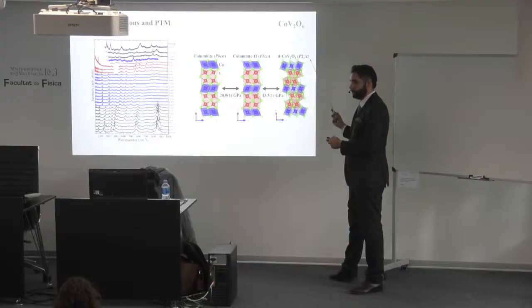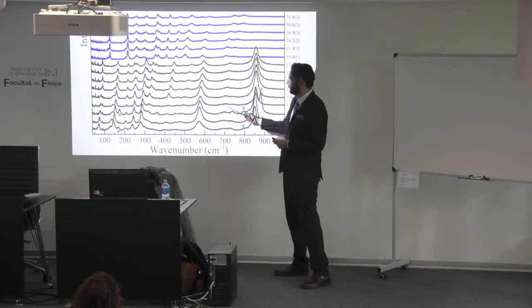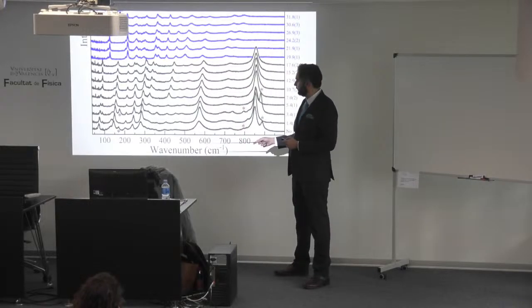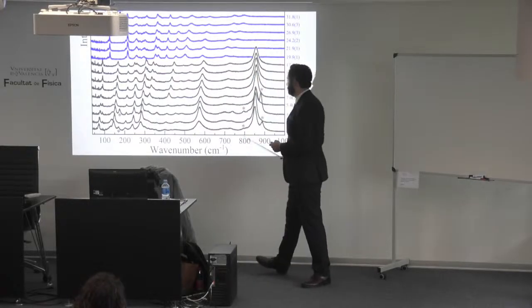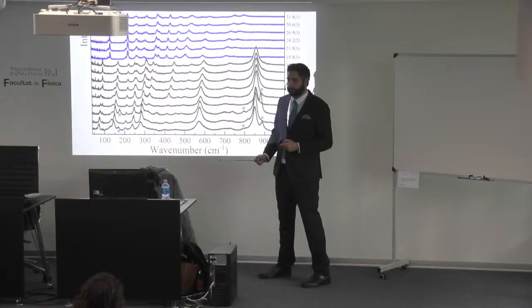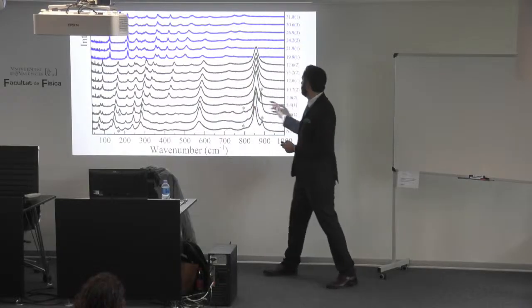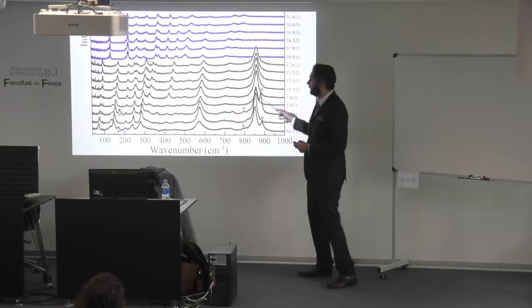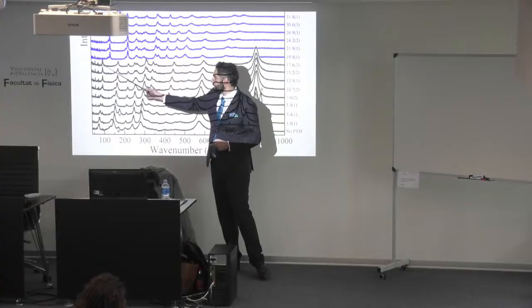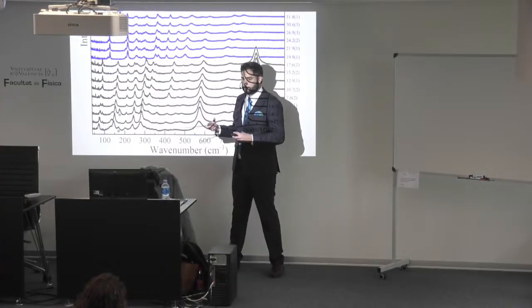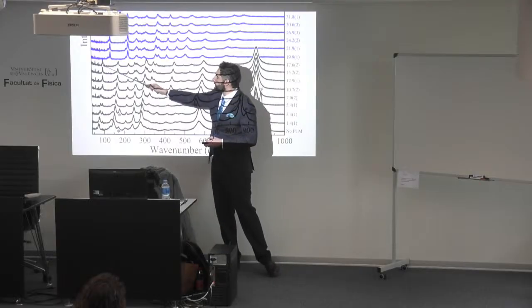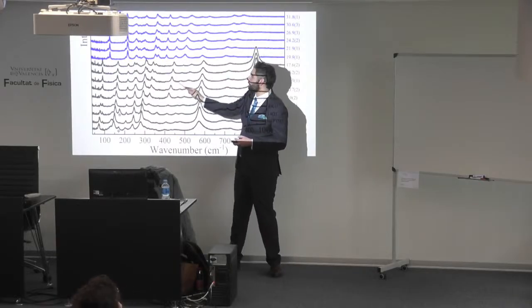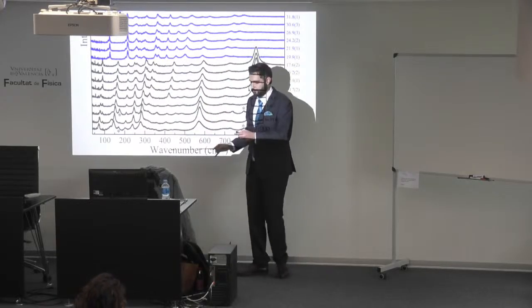We also see these transitions in Raman. In this case, we start with the columbite with some extra peaks that I'm going to discuss in the impurity section. And when going to 20 GPa, the modes are the same but jump to the right. So this volume collapse but still being the same structure permits that this goes here, this goes here, this goes here. So it's the same but shifted to the right.